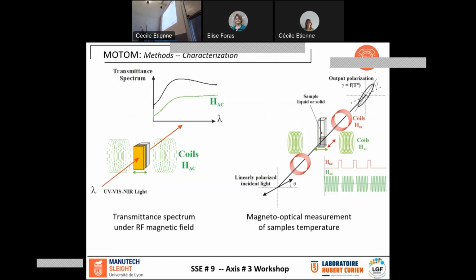So what we are planning to do is to alternate. First, we apply the alternating magnetic field to heat the samples. Then we stop. And with a fixed magnetic field, we just measure the output polarization, and we can then see if this polarization is changing or not, and deduce at the end the nanoparticles' temperature.